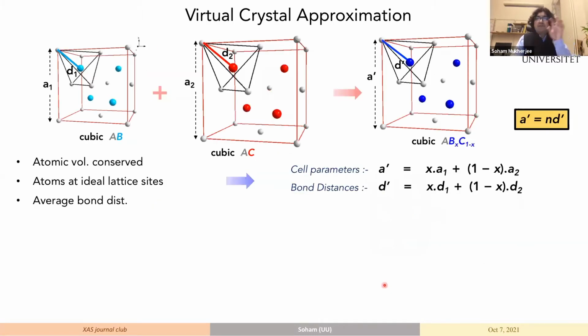So if we look at a crystal, how does it look? Let's say we take a cubic system, AB and AC, and we make an alloy of the two, ABC. Now, when you look at the local tetrahedra, we will see that this distance and this distance are the initial distances of the two end members. Now we have a distance where the distance between these two atoms now scales exactly in the manner in which the lattice parameters scale.